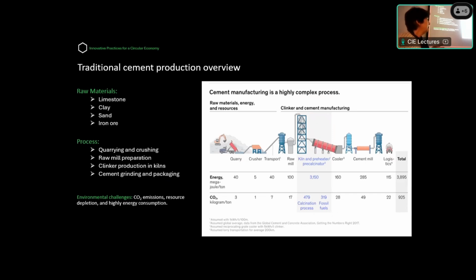I have shown in the right image how much energy is consumed and how much CO2 is emitted at the different stages, which I got from McKinsey, if I want to be honest with the reference of the image. As you see, the main energy consumption and the main CO2 emission is in the middle part, which is calcining and burning fossil fuel. That consumes around 3 gigajoule per ton out of the 4 gigajoule per ton we need for producing cement. CO2 emission is mostly due to the calcining reaction and also burning fossil fuel: 50% due to the calcining reaction and 30% due to burning fossil fuel.